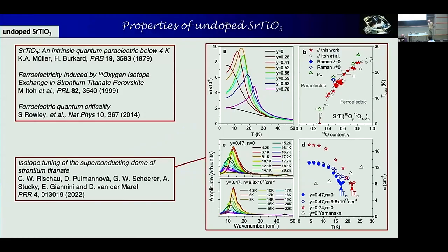So first of all, the properties of undoped strontium titanate. Strontium titanate in its pristine form, if you use normal oxygen, oxygen 16, is an insulator. It has a gap of 3 electron volts. It has a high electrical polarizability. The dielectric constant is about 2000, so that's a lot. And so it's easily polarizable.